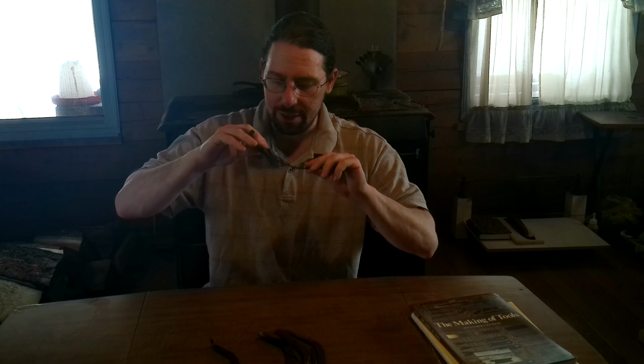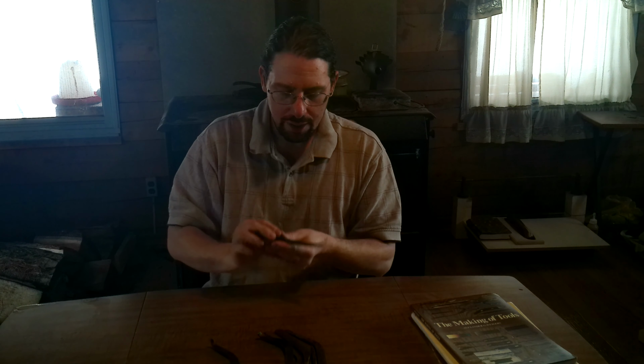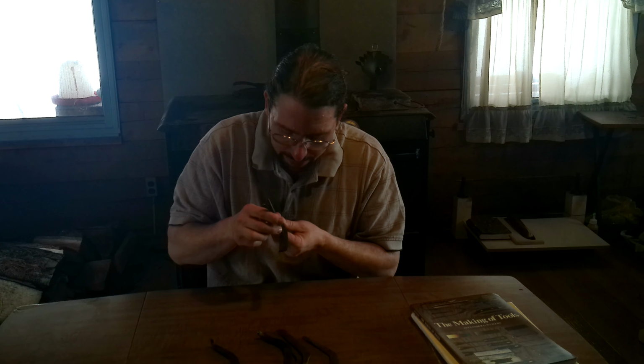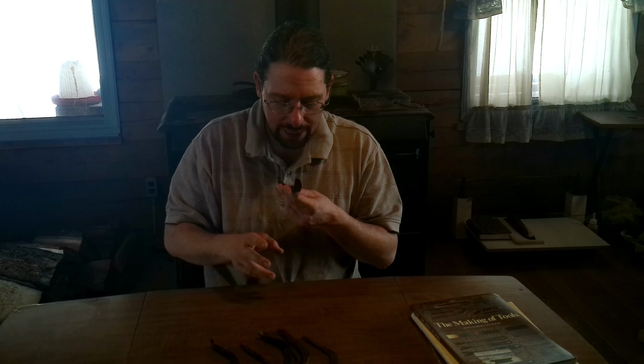You do want to look at these once you get it all nice and polished and look for cracks and inclusions. It's a final check. Again, these are recycled steel. Some will fail at no fault of yours. Right? You can do everything perfectly and still have a blade fail. Some will. A couple of these have some small inclusions where probably a little bit of rust popped out. It won't pick up in the camera, but there's one right here in this blade that I'm pointing to. Okay. I can probably file through that. It's not a crack, it's an inclusion.